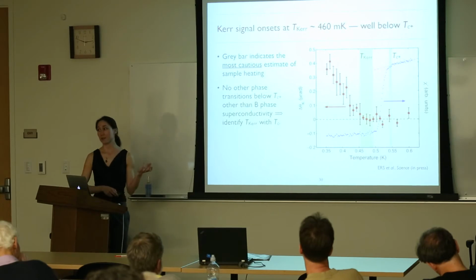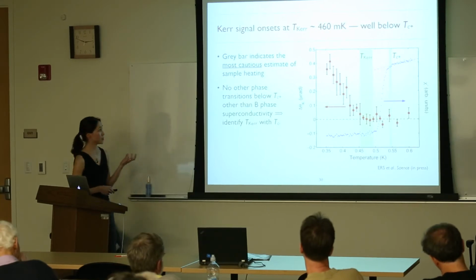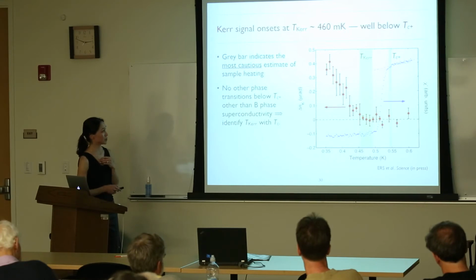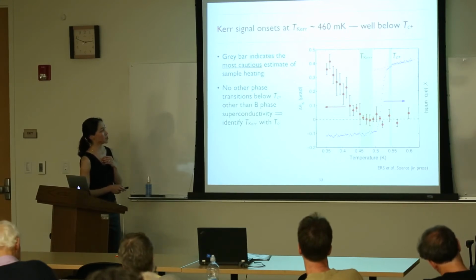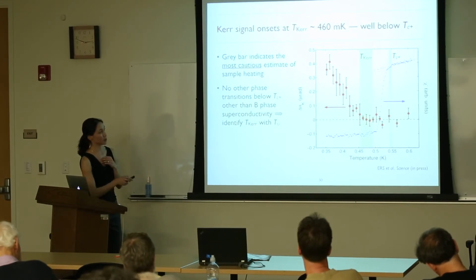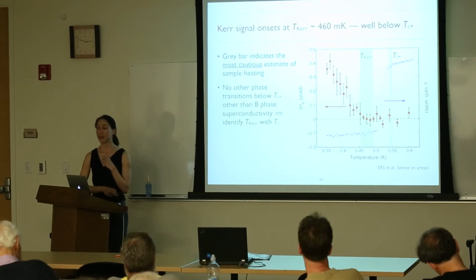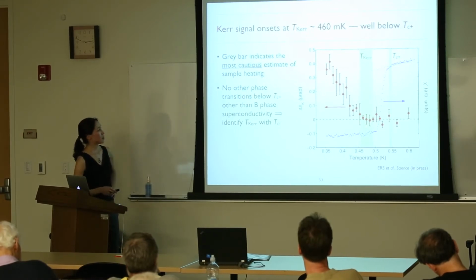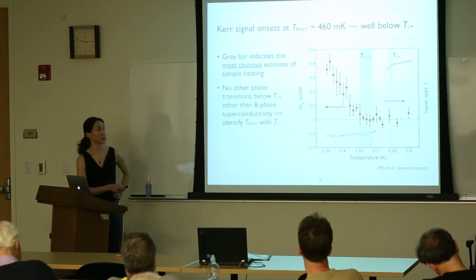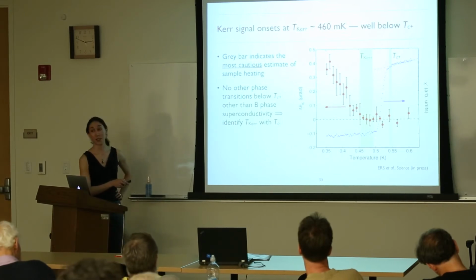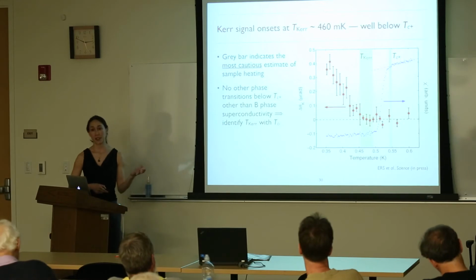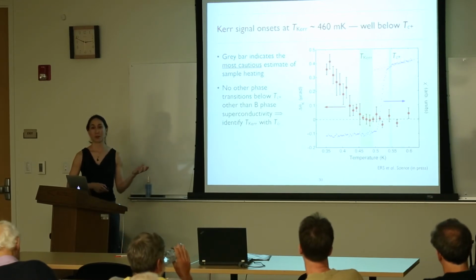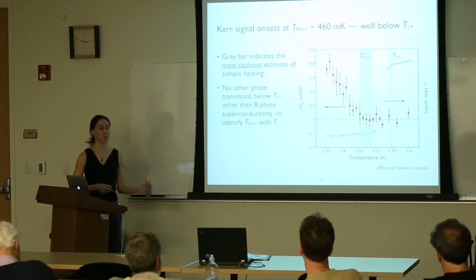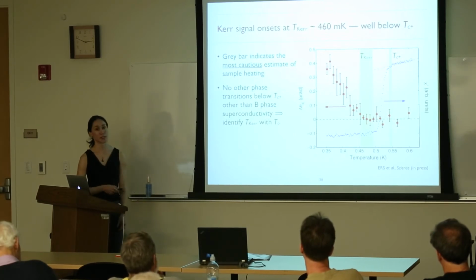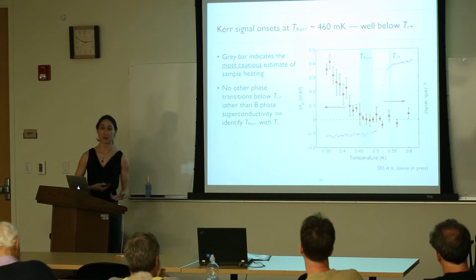And again, we want to take sample heating into account. There are a few ways to do this. It's hard to do it experimentally, so what I've also done is some simulations. At any rate, the worst the sample heating could be is basically indicated by this rather thick gray bar here. But the point is, even taking that into account, there's a clear separation between the Kerr effect transition temperature and TC+. And since there aren't any other phase transitions going on in this region, we really have not much choice but to identify the onset of Kerr effect with the onset of B phase superconductivity at TC-.